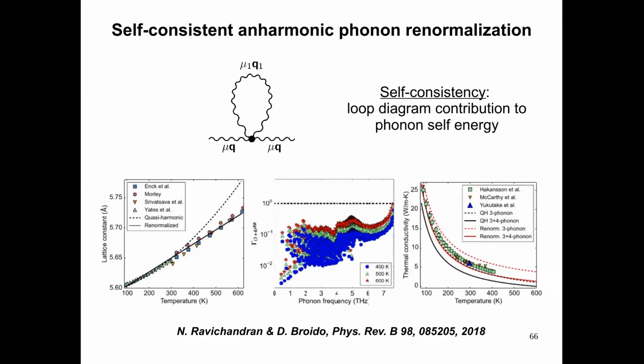And when we included this renormalization, we not only got excellent agreement with the experiments for lattice constants, the phonon quasi-particle picture is now well behaved. Gamma over omega is much lower than 1 for most phonons. And the thermal conductivity that we get, that is the red solid curve on the figure on your right, lies very close to the experimental data.